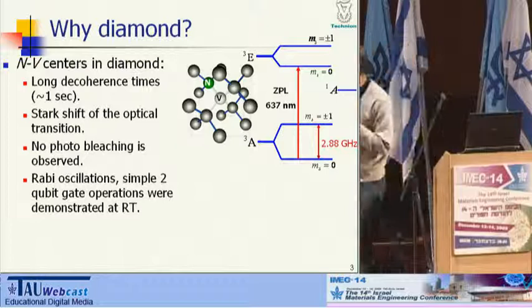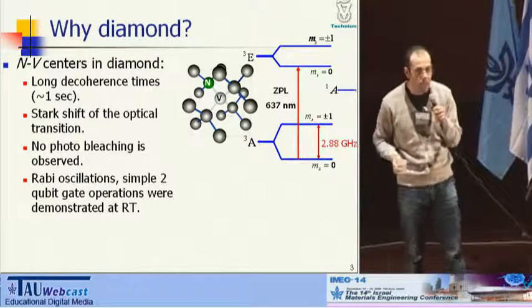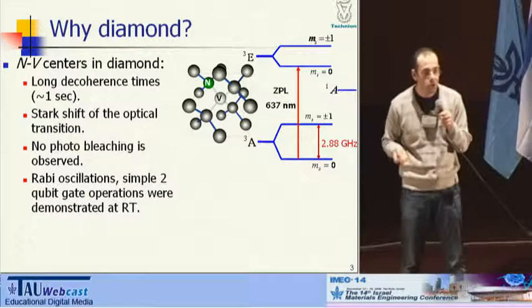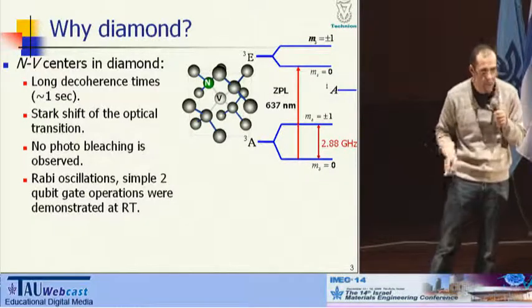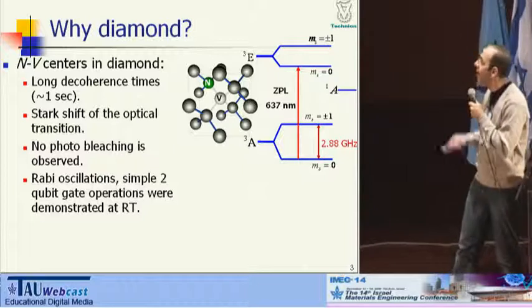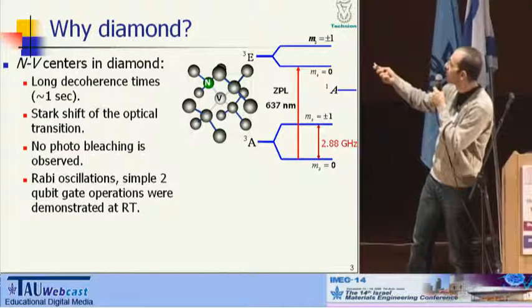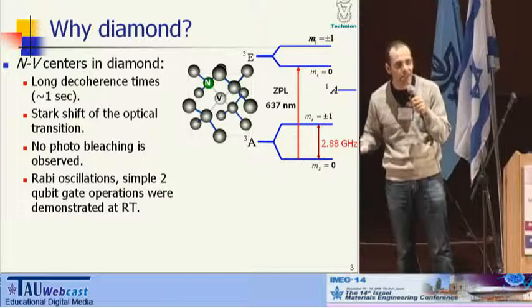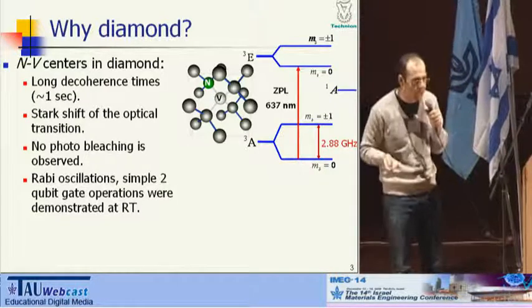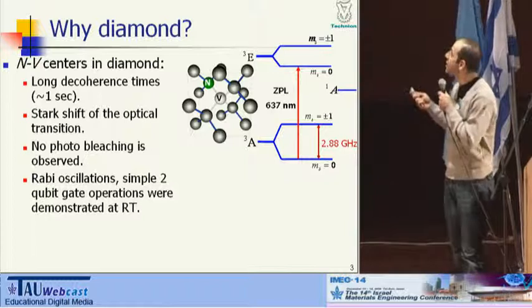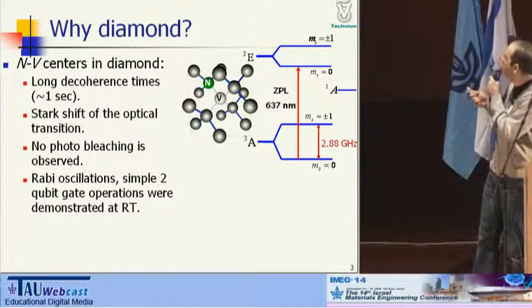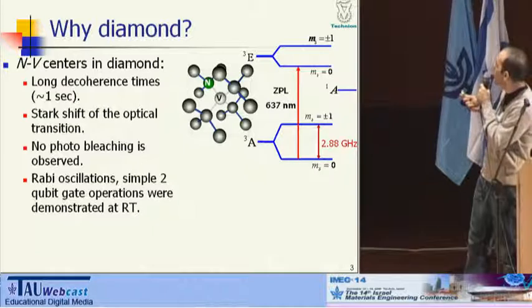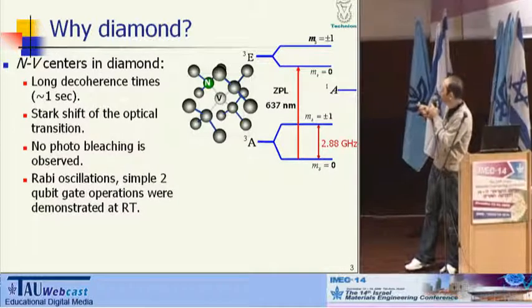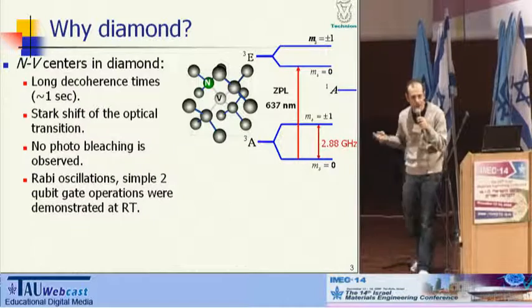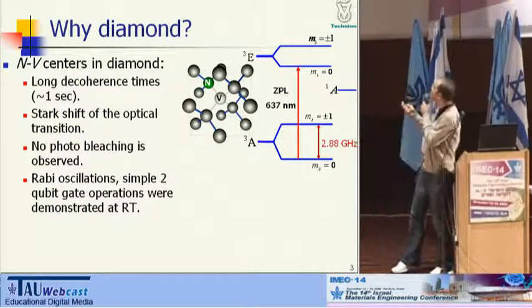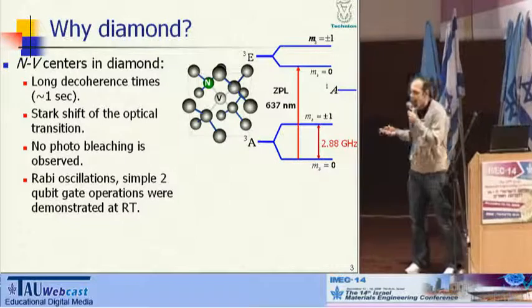So the first thing is why diamond? Actually, as all of you know, diamond is an extraordinary material, not only due to its mechanical and optical properties, but also quantum mechanically. If we take a diamond structure and substitute a single carbon atom with nitrogen and a vacancy, we obtain a nitrogen vacancy color center, or NV center for short. Its energy diagram is shown here. Its ground state is formed of a triplet, while its lower ms equal to 0 state is optically active and can be read out with a standard solid-state red laser, and its upper state, ms equal ±1, is optically inactive.